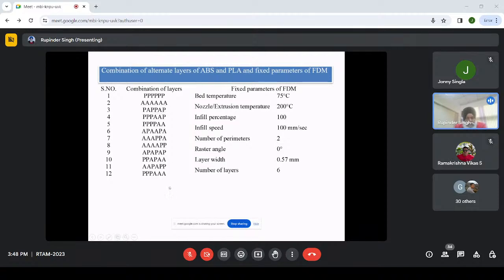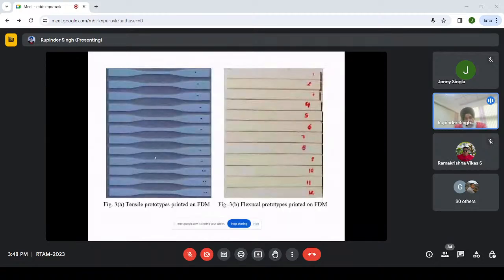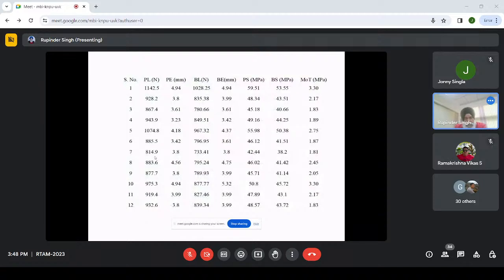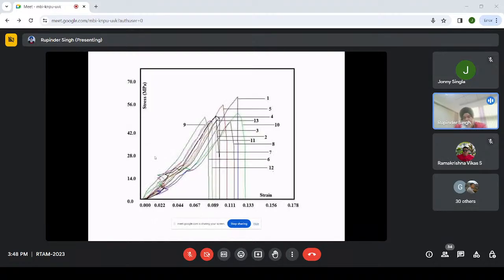So this was tried at random. What we observed, the failure pattern for the tensile and flexural coupon, they followed a specific path. This is the printed coupon. These are the observed peak load, peak elongation, break load, break elongation, peak strength, break strength, and the modulus of toughness. So this is the typical stress strain curve.